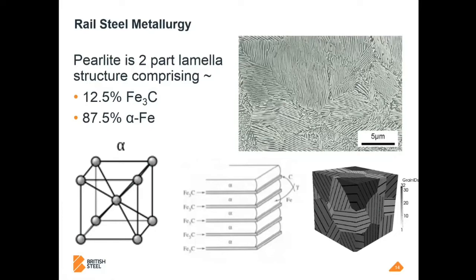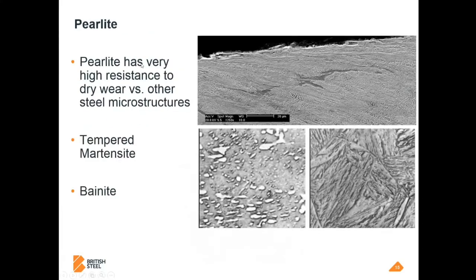The transformation happens on the cooling bank somewhere, and these nodules, these colonies of pearlite, grow from the prior austenite grain boundaries in random orientation. So presented to the wheel on the running surface, you have randomly orientated colonies of pearlite. However, in service, even with the increased strength, you do get some plastic deformation of the surface layer. And this is a curved section of track.